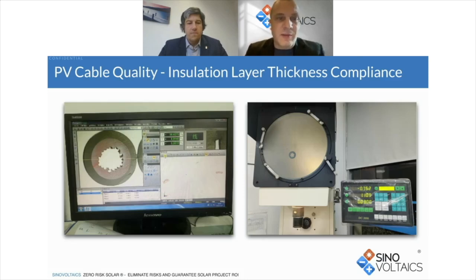Then, in line with ascertaining material property compliance, another common test done at the factories involves the measurement of thickness of the insulation layer between jacket and conductor. There are both manual and also more advanced and precise computer-linked microscope testing devices with which the compliance with these minimum thresholds of insulation layer thickness can be measured.